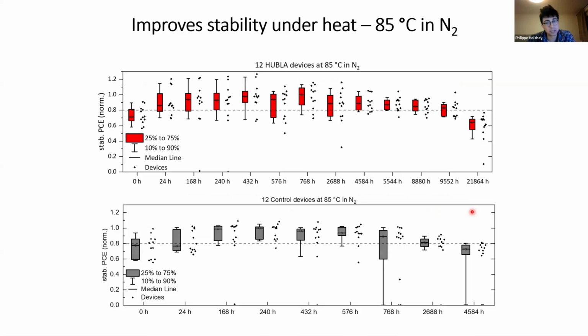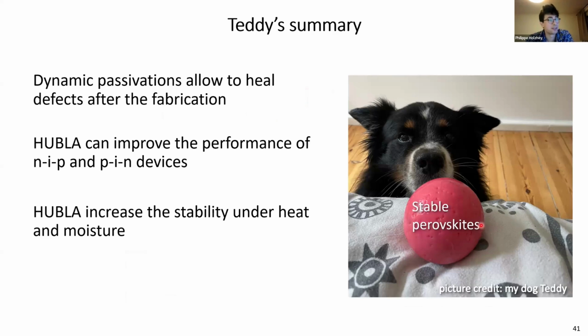And this is some data I measured in Oxford. So this is at 85 degrees in nitrogen, and I measured 12 devices over time, and they improved. So I normalized it to the peak median efficiency at around 768 hours. Then after 2.5 years, the devices degraded to below 80% of the peak median efficiency, while the control devices reached that in 4,500 hours. So Teddy loves balls, I guess, just as we love stable perovskites.